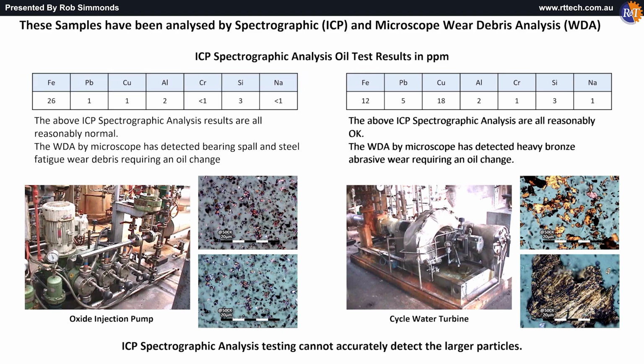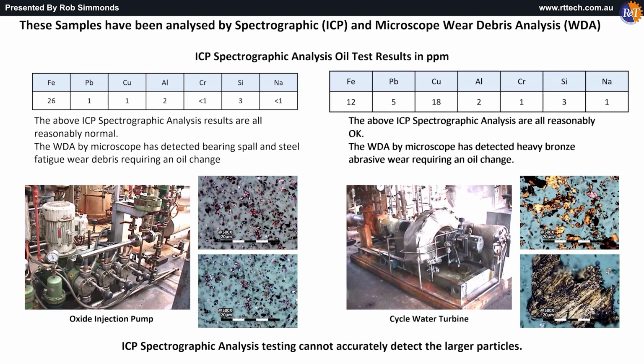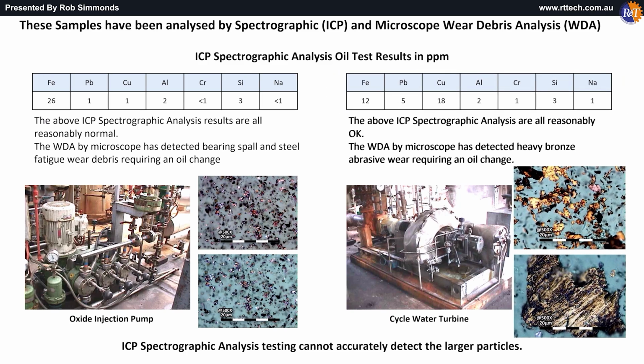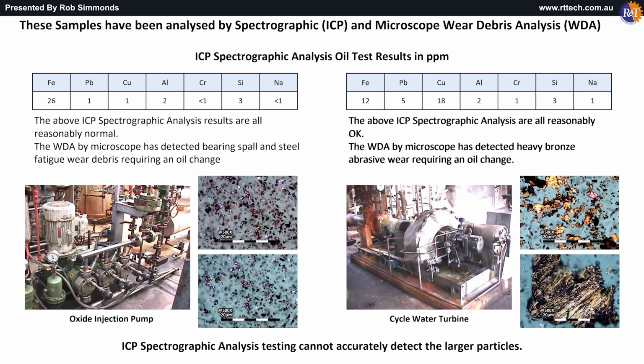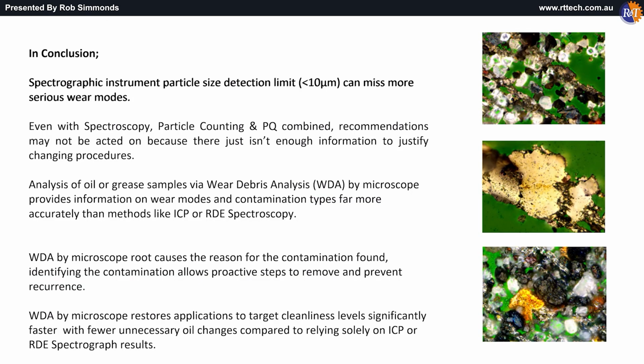On the right-hand side, the above spectrographic analysis results are all reasonably okay. When checking the oil sample with the microscope, we can see there's heavy bronze abrasive wear that requires an oil change, displaying the difference in detection limits between analysis methods. Spectrographic instrument particle size detection limit, less than 10 micron, can miss more serious wear modes.